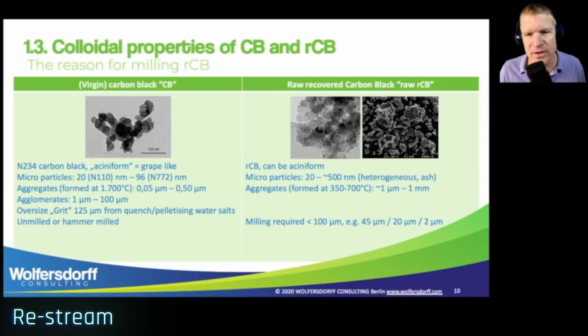Now let's look at a recovered carbon black. Recovered carbon black contains carbon blacks which are recovered, so it can be a grape-like. It can have the structure similar to carbon black. The microparticles are quite different though, because here we have a heterogeneous material. It's not only carbon black. We have the ash content, we have carbonaceous residues, we might have some volatiles. And the microparticles are anything between 20 nanometers, which is the smallest size of the carbon black, and 500 nanometers, which could be bigger particles of the ash content.